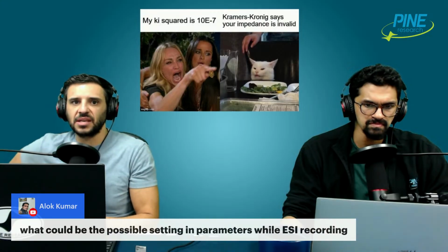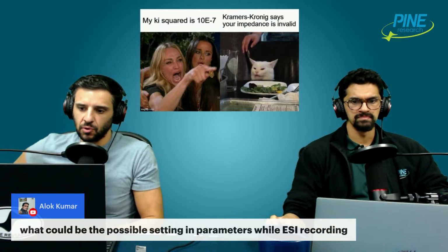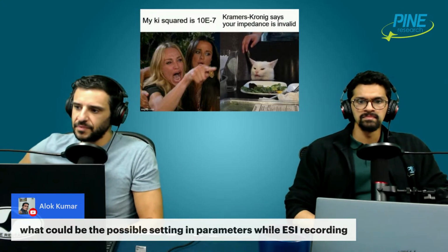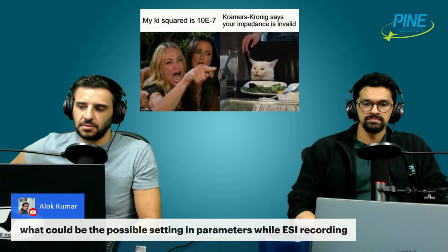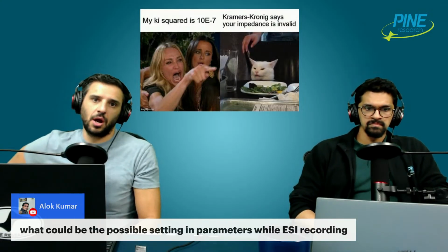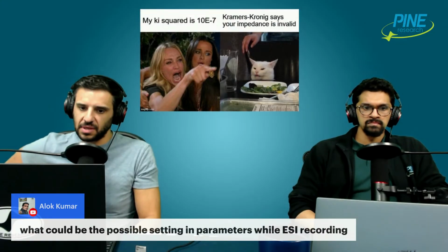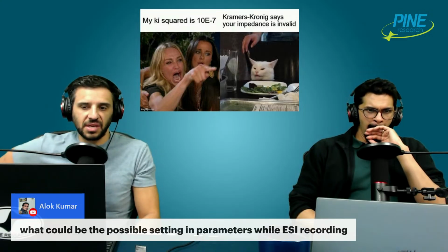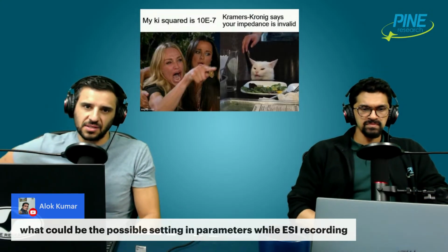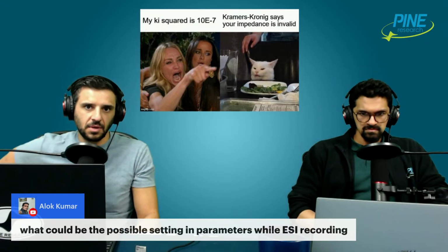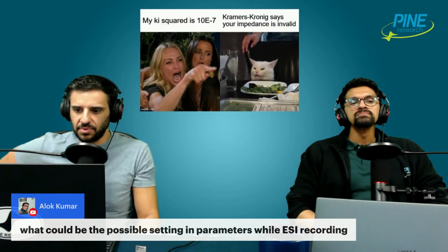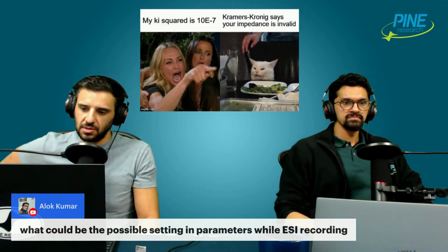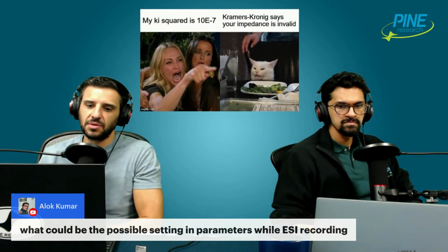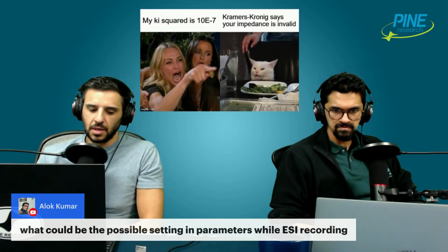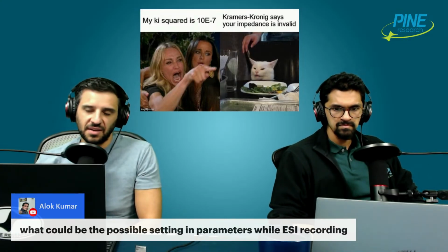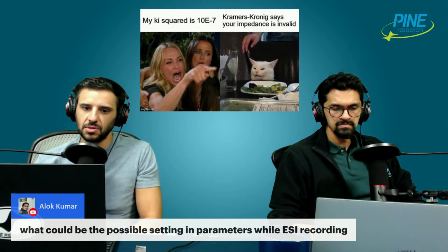If what you're asking is what parameters you should pick, as a very general rule, if you're studying impedance on an aqueous 3-electrode system, HER, OER, ORR, something of that nature, most probably you should be doing potentiostatic impedance. Most probably you're going to have somewhere between, let's say, 5 and 20 millivolts amplitude. You're going to want a smallish amplitude to start, and then you can increase it if your data looks noisy. Sometimes increasing the amplitude helps clarify that noise. So somewhere between 5 and 20. I usually start with 10 to 15 millivolts as my go-to.